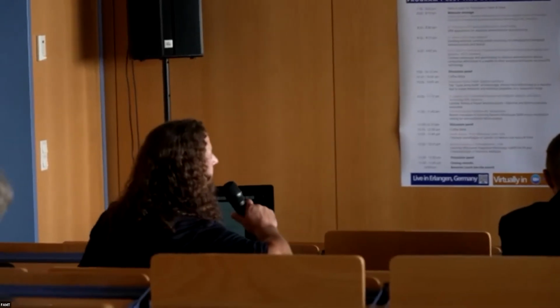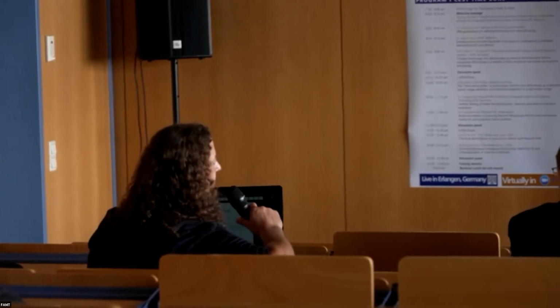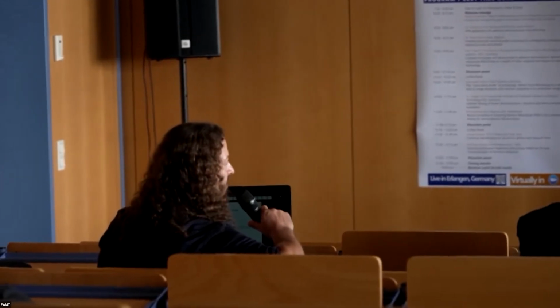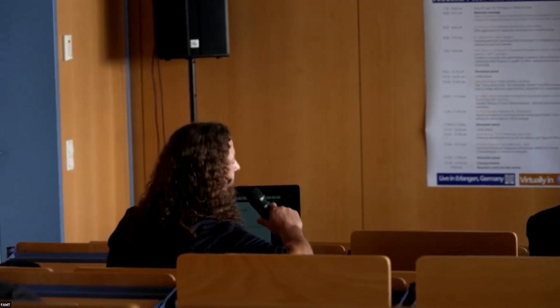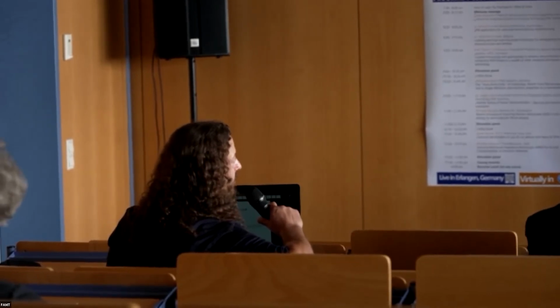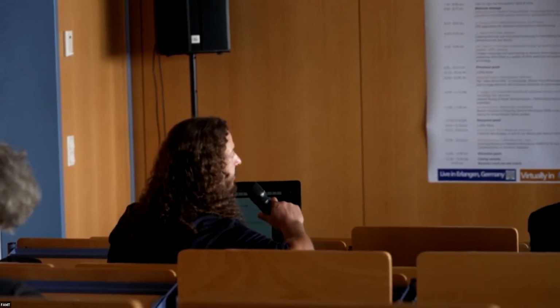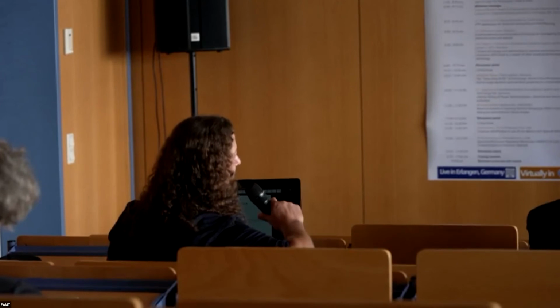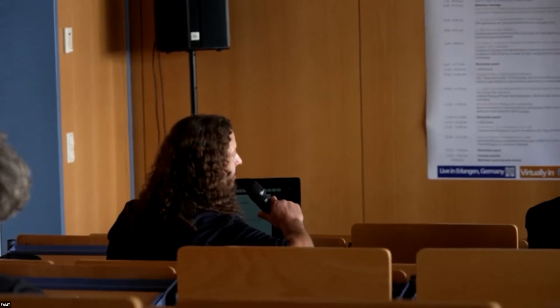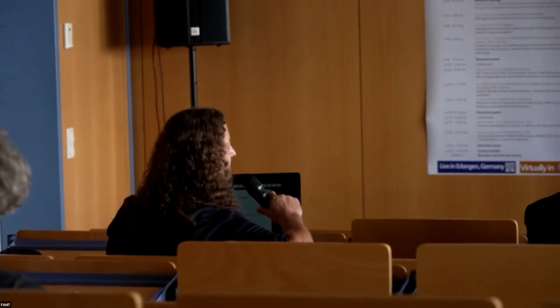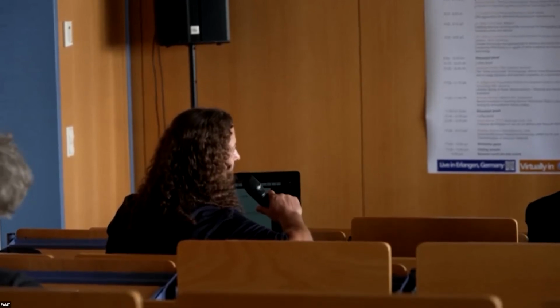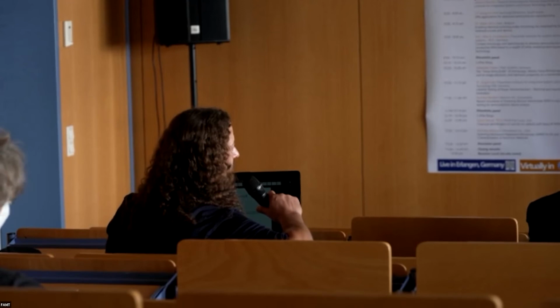Hi, Sigli. Good question. We haven't done any measurements on these kinds of samples in a glove box. However, we can flood our high vac chamber with different inert gases, for example argon or nitrogen, and then also influence the humidity level in that regard. However, the water layer on most samples is quite resilient, and just by simply flooding the system with inert gas, it's kind of hard to remove all the water content. So we sometimes even apply an annealing step within the vacuum to really remove all the water. I can't really give a more precise comment than that.